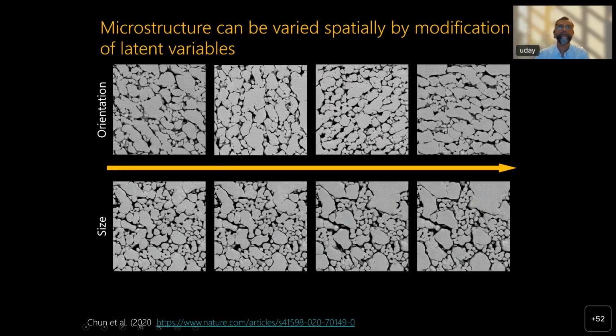For example, here we can control the orientation of the crystals or the voids. In fact, we've shown that depending on the void orientation, the sensitivity of the material can change massively. Voids that are oriented along the shock propagation direction tend to be more sensitive than voids that are oriented normal to the shock propagation. So we can actually investigate effects of orientation of voids and so on. And so we can now manipulate the microstructures virtually to get different void orientations.